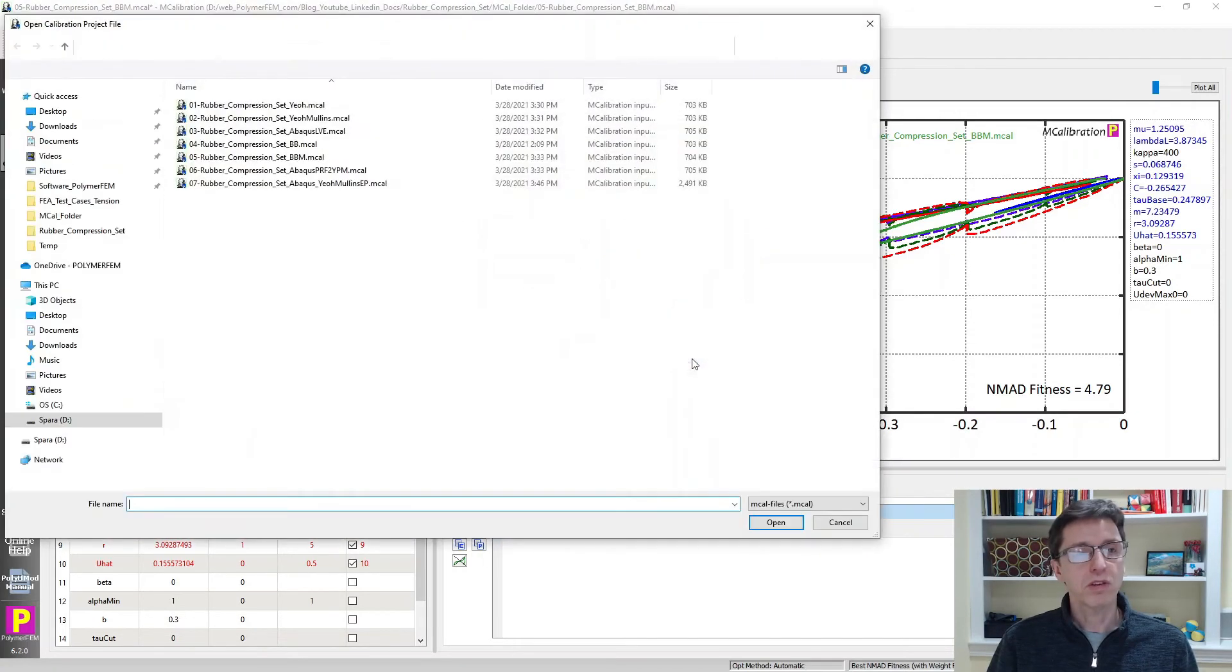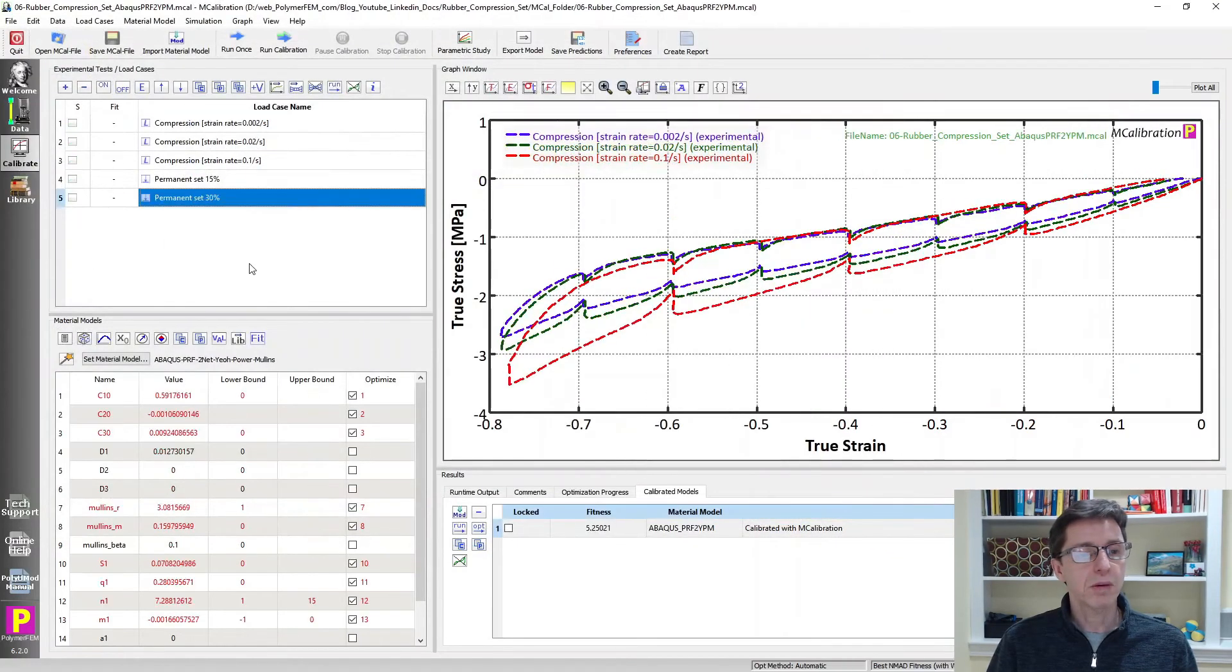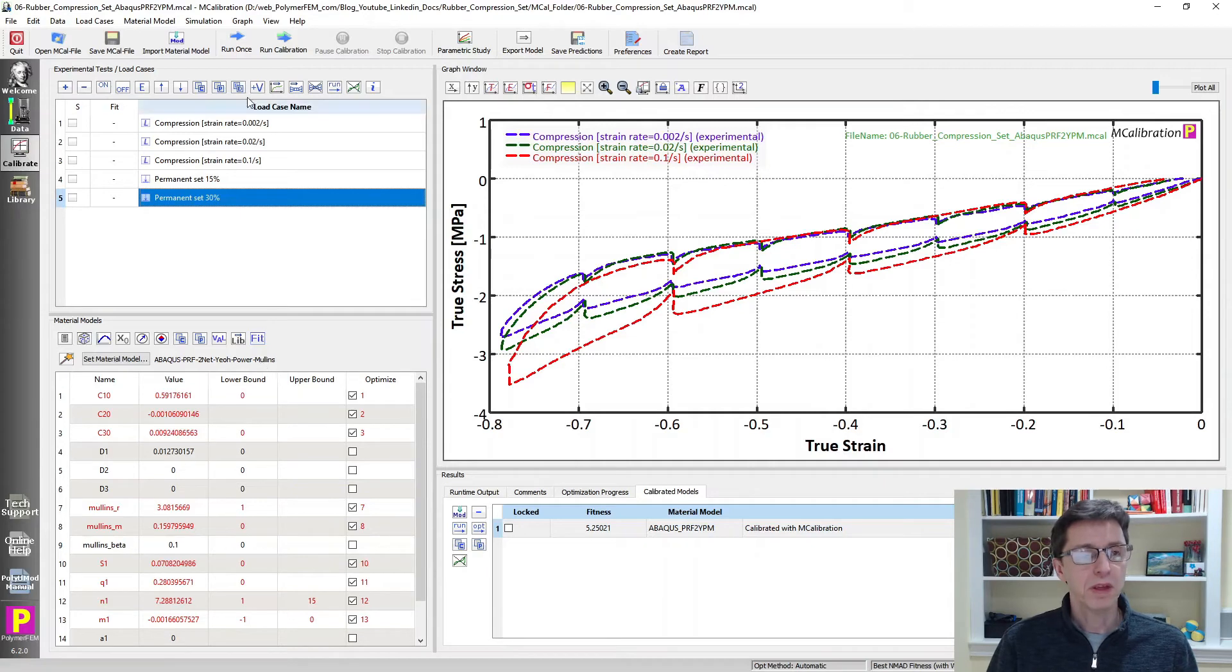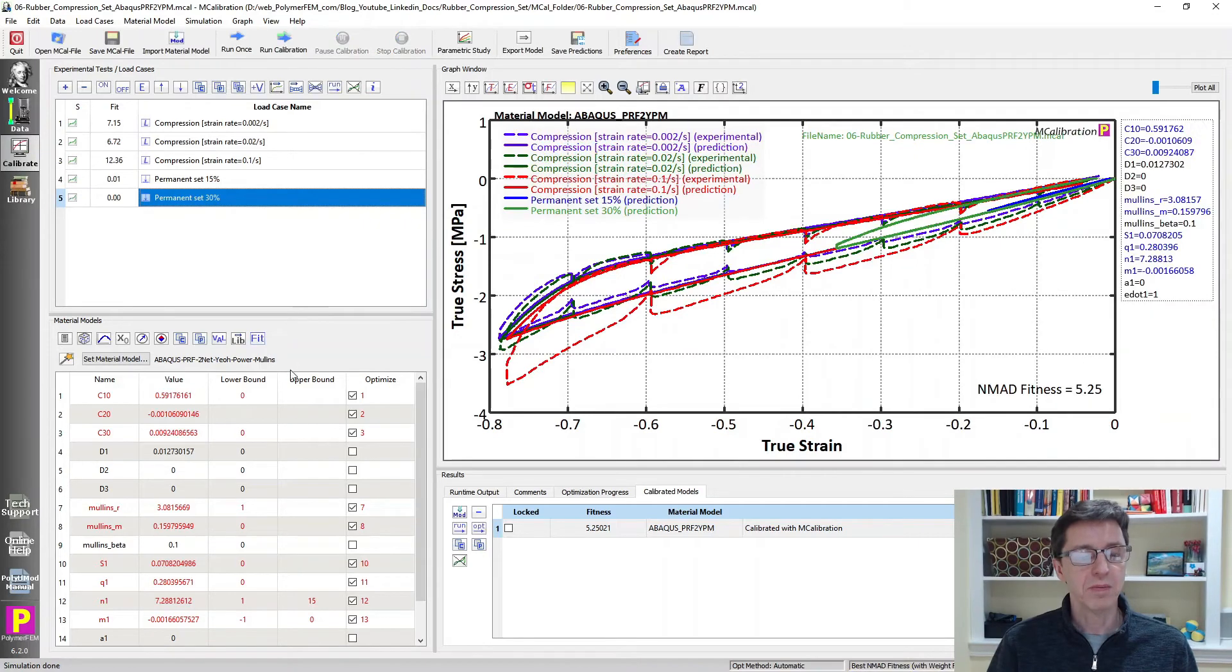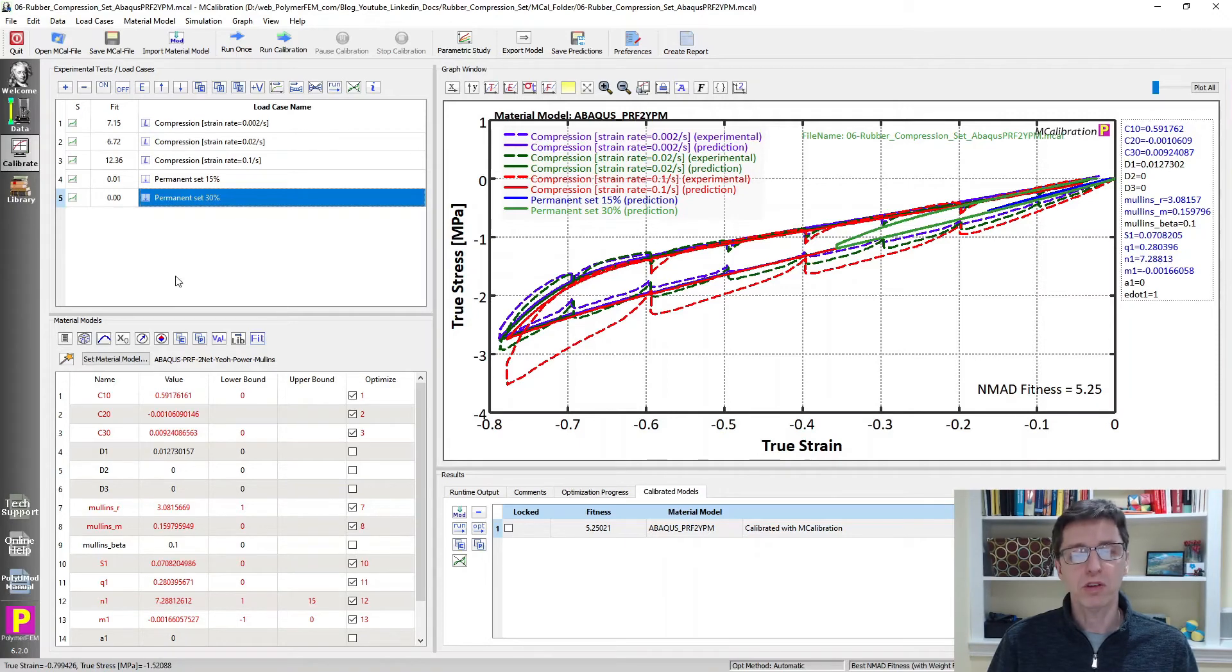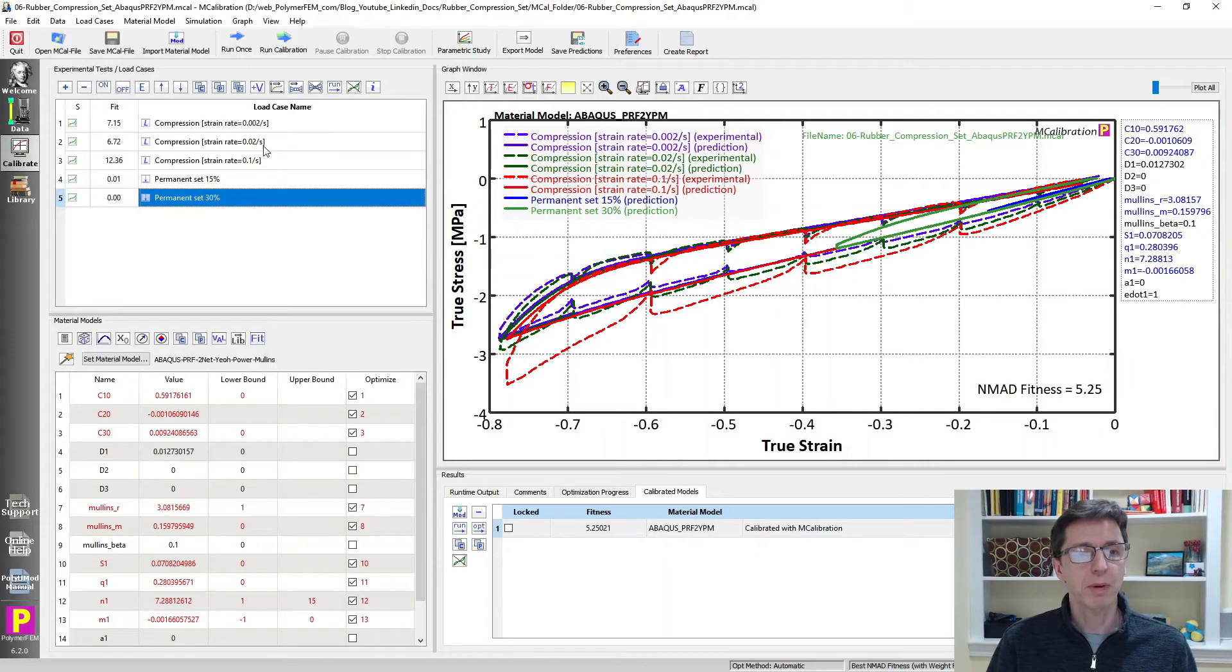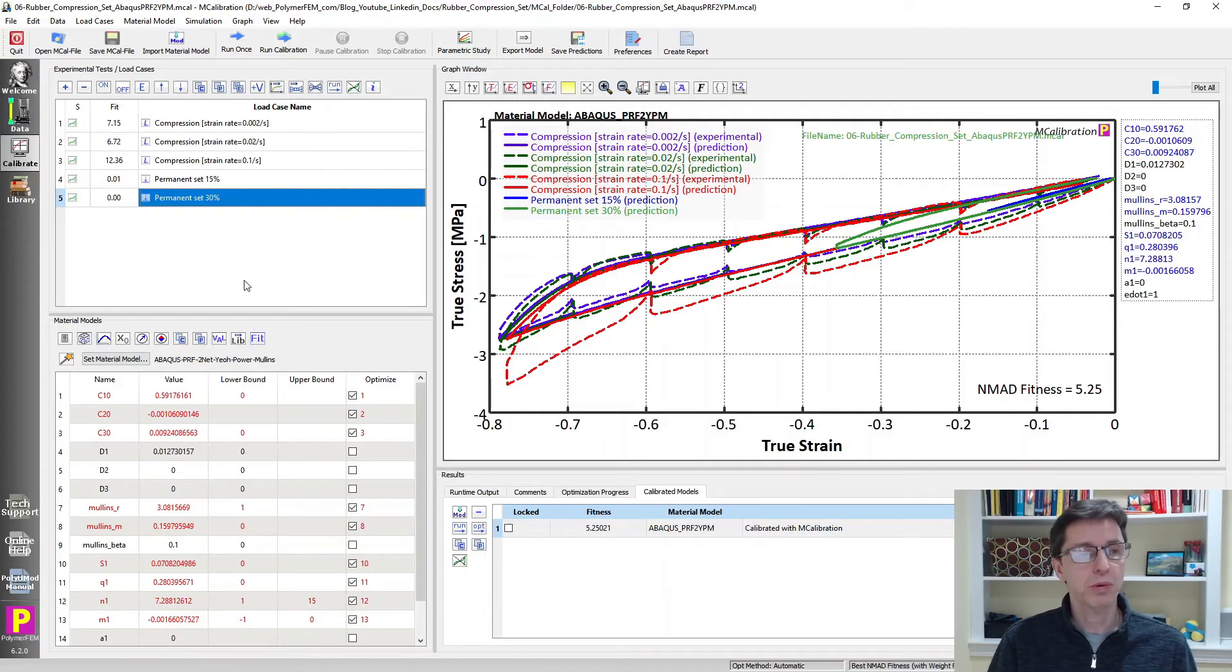So let's try something else. Let's try an Abaqus PRF model. So this is an Abaqus parallel rheological framework. It's a two-network model, Yeoh hyperelasticity power law flow, and Mullins damage. So this is actually not all that different than the model we just talked about. It's just called something else, and it's slightly different elements to it. And the error is 5.2%. So it's not quite as good as the one we just talked about, but it's still pretty decent. We get very good predictions of the permanent set and a little bit less accurate of the compression set. You can kind of select which of these two types of data that you want to emphasize. But this is another reasonable approach for permanent set predictions of these types of materials.